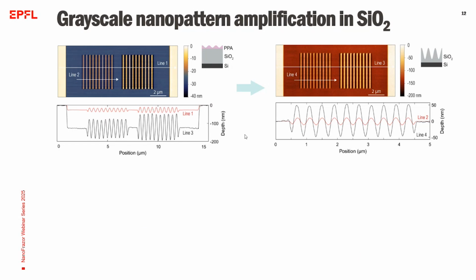And as a result, with this optimized plasma process introduced in the last couple of slides, we amplify shallow polymer patterns written on thermally sensitive resins. We amplify polymer patterns into SiO2, as seen in these figures. Sinusoidal nanopatterns, as you can see here, are amplified in depth 5 times in this example, while preserving the same sinusoidal periodicity.